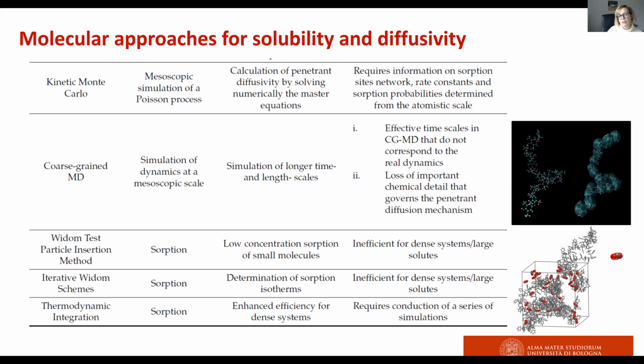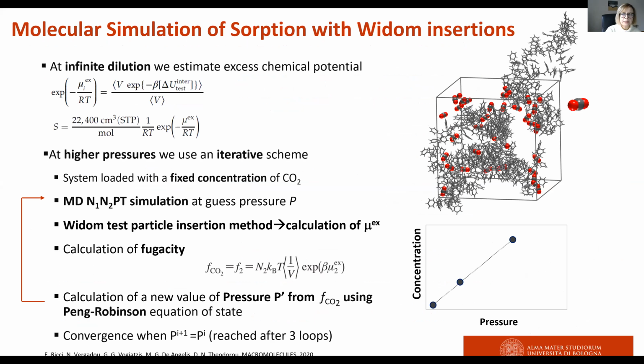Solubility can be predicted using the test particle insertion method, such as that invented by Widom. And in particular, there is a slide here that shows you how to calculate this solubility with molecular techniques. You can insert a test particle and calculate what is the interaction energy between the particle and the surroundings. And this is directly related to the solubility. If you are at infinite dilution, you insert the molecule into a pure polymer. And this is a very easy calculation.